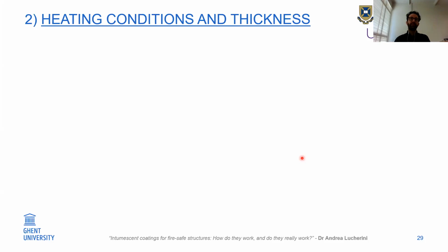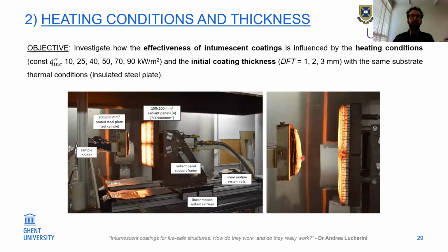Then, the second study that I want to present today focuses on the influence of the heating conditions and the thickness. So the objective of the study: I used the same experimental setup with the same radiant panels, the same steel plates, 200 by 200. But in this case, I looked at the influence of the heating conditions. I used 6 different heat fluxes: 10, 25, 40, 50, 70, and 90 kilowatt per square meter, and initial coating thicknesses of 1, 2, and 3 millimeter, with the same substrate thermal conditions, so an insulated steel plate. And I wanted to look at the influence of different parameters on the effectiveness of intumescent coating.